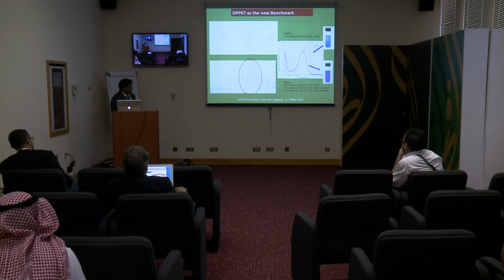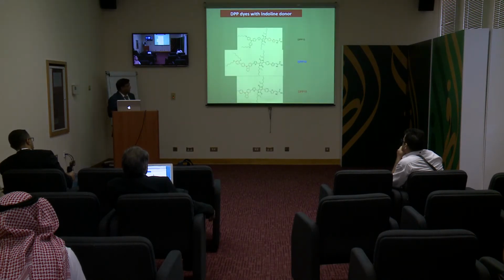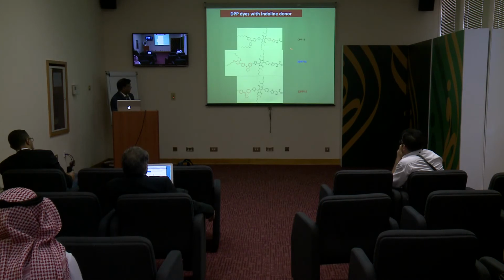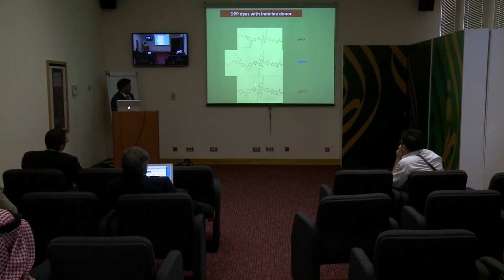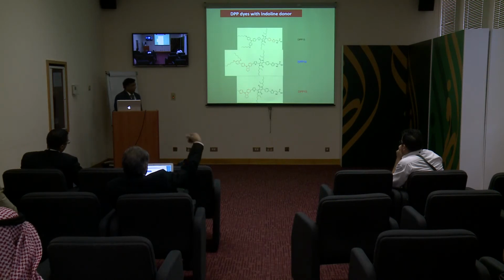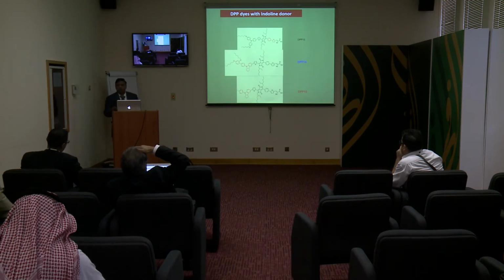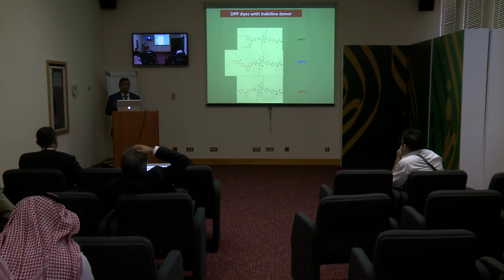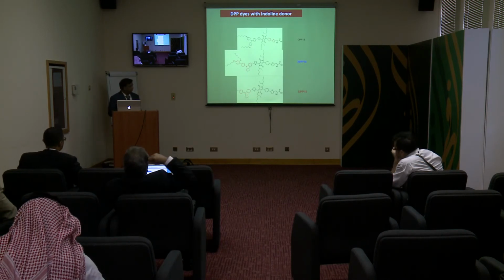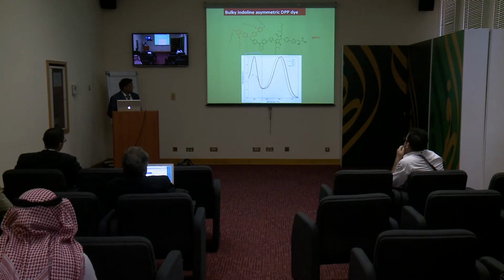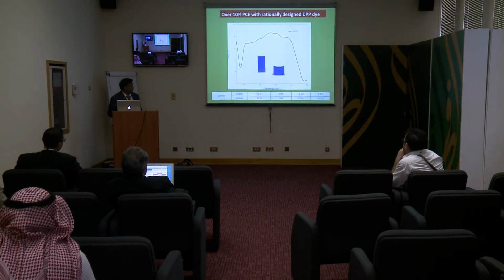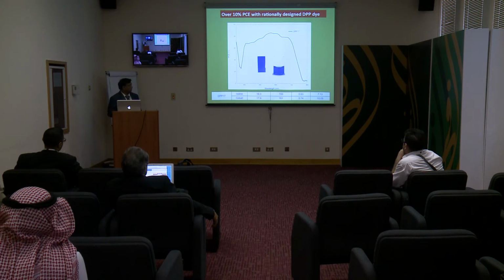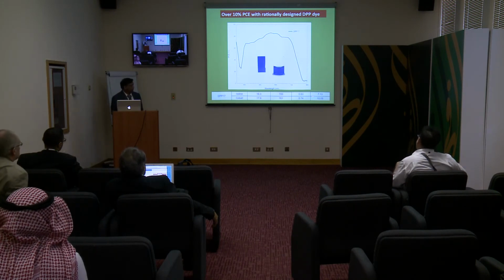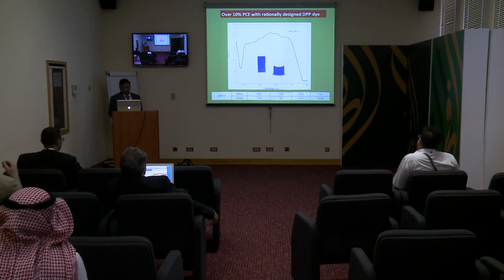Because of this experience, we tuned a little bit on the different donors. Here, only the donor part we are changing, and as with the experience of this cobalt complex, the bulkier the donor, we have less recombination and a higher VOC. Here you will see that the photovoltaic performance increases with the donor, and you get more than 10% efficiency.